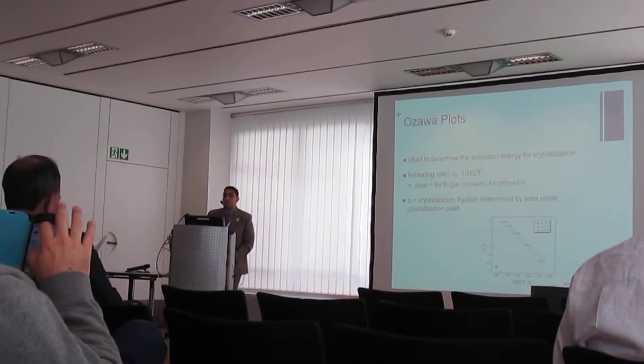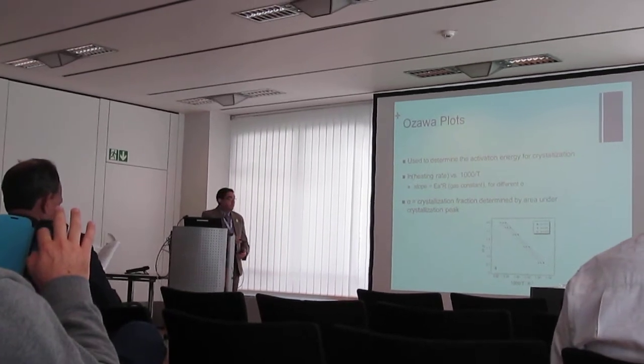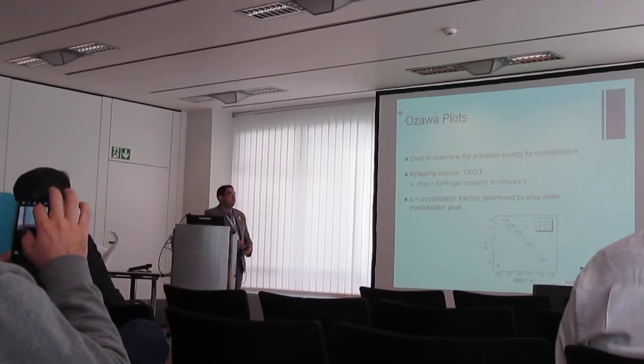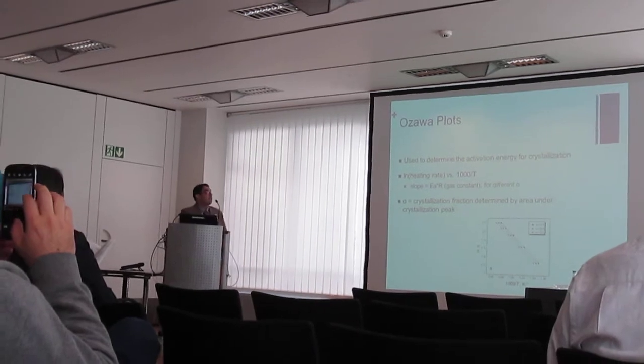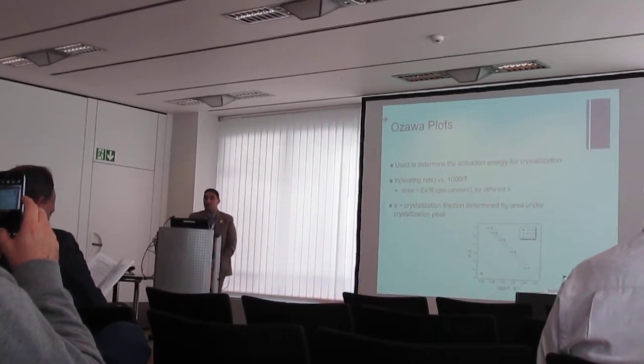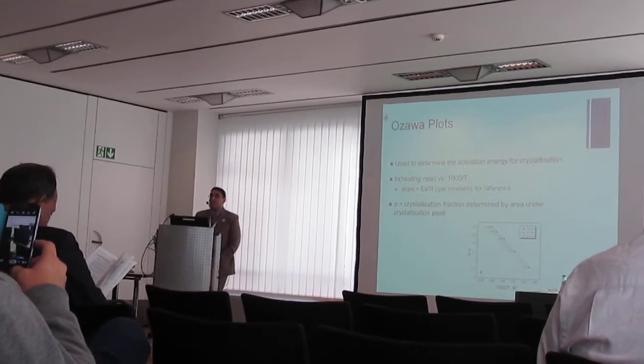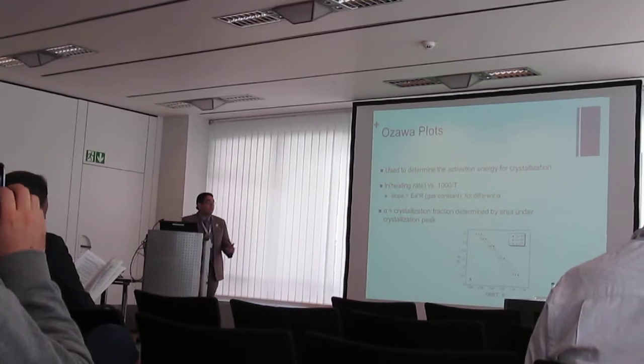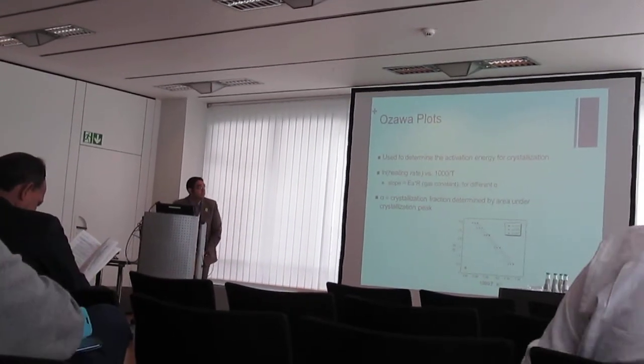We used 5 different heating rates, and we were able to find an Ozawa plot like this that I'll show you. What the Ozawa plot shows us is that the slope of this curve gives us the activation energy of crystallization over the gas constant for different alpha, where alpha is the fraction crystallized, which is determined through the area underneath the crystallization curve.